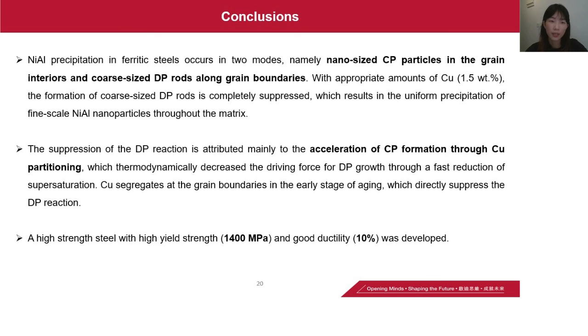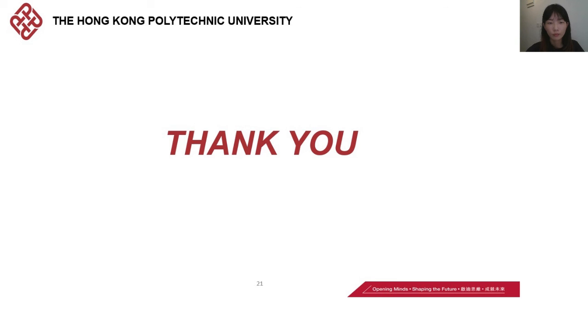So here are our conclusions. The first is that nickel-aluminum precipitation in ferritic steel occurs in two modes, namely the continuous precipitation and discontinuous precipitation. And the suppression of the discontinuous precipitation can be attributed mainly to the acceleration of CP formation by copper partitioning, and on the other hand, copper segregation at grain boundaries can directly suppress the DP reaction. And we also obtained a high-strength steel with high yield strength and good ductility. Okay, that's all.